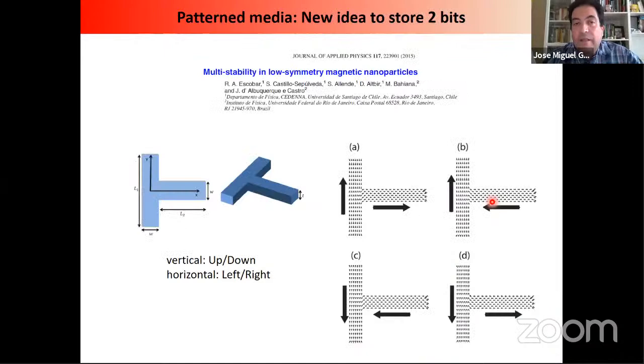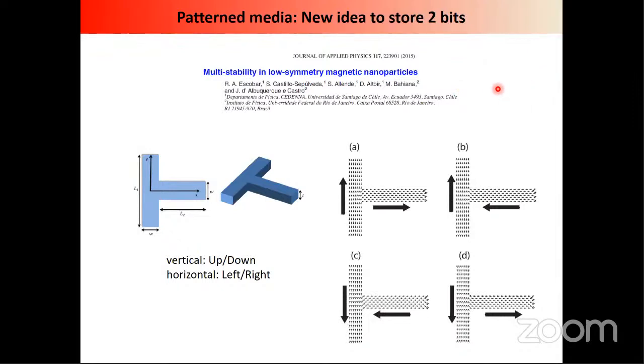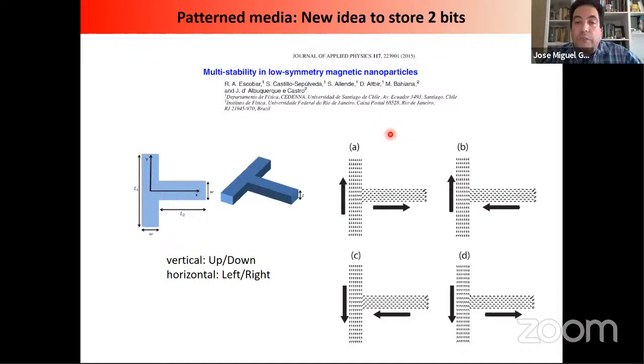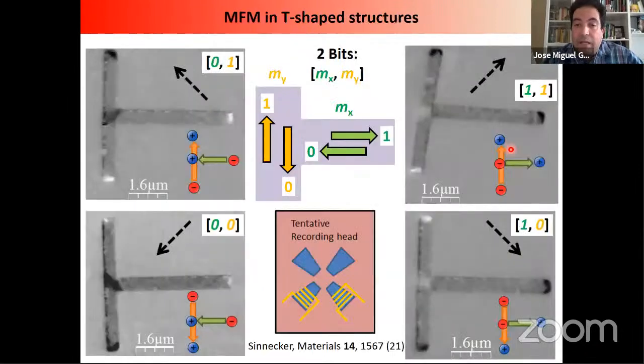And finally, in the case of these artificial nanostructures with T-shaped structure, this is an idea that came from Chile and Brazil. Yes, thank you. And they proposed to use this T-shaped structure to store 2 bits of information, 1 bit given by the vertical branch pointing upwards or downwards, and the other by the horizontal branch pointing rightwards or leftwards. So that was a theoretical proposal. And then at the CBPF, João Paulo's group fabricated the structures with e-beam lithography, and we looked at them using magnetic force microscopy. So you can see that was the initial field. We removed the field, and this structure is stabilized in this state, bright and dark, so vertical upwards, bright and dark leftwards.